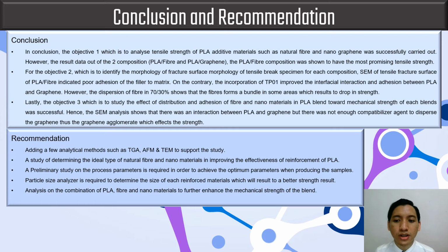Lastly, in conclusion, objective 1, which is to analyze the tensile strength of PLA additive materials such as natural fiber and nanographene, was successfully carried out. However, of the two compositions, the PLA fiber composition was shown to have the most promising tensile strength. For objective 2, which is to identify the fracture surface morphology of tensile break specimens for each composition, SEM of the tensile fracture surface of PLA fiber indicates poor adhesion of the filler to the matrix. On the contrary, the incorporation of TP01 improved the interfacial interaction and adhesion between PLA and graphene.